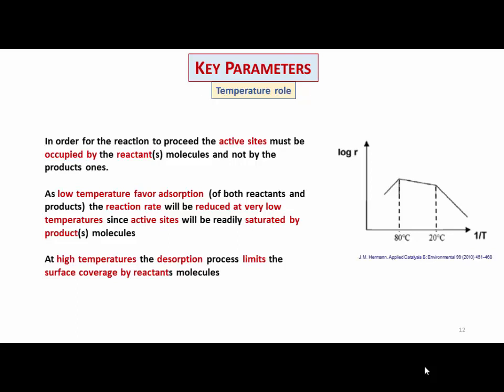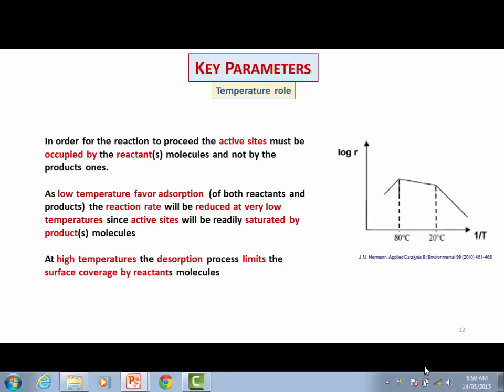The role of temperature, as I said before: the first thing people say is there is no effect of temperature. It's not true. It is even much more complicated than normal. That is because you have a few things that depend on temperature. If you go down to very low temperature, what you see is that there is nice absorption, maybe, but then the reaction rate will not be able to grow because the product will not leave. When you have high temperature, you have desorption, so your molecules are coming and going again, and you are dropping. So there is a region, which depends on the process you are using, but is normally in this range, where you have an optimum temperature for getting the best of your system.